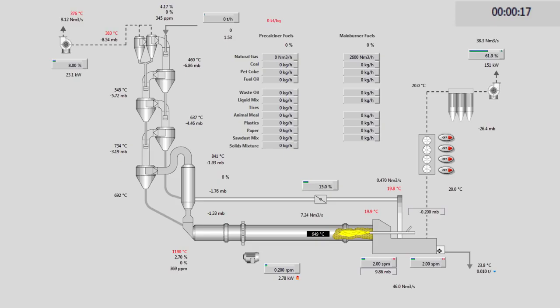Now that we have revised the theory, let's go into practice mode. As seen earlier, full feed is 200 tons per hour, 30%, 60 tons per hour. At the moment we have enough oxygen. In addition to the ID fan, we also have a natural draft created by the 5 stages preheater. We are ready to add the 60 tons per hour. Keeping an eye on the O2, it will drop drastically once the feed is in the system.